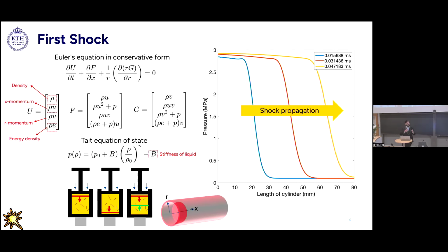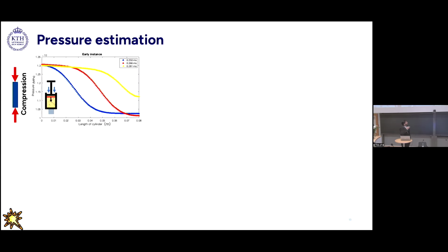And while the contact between the impactor and the piston is established, that will send in another shock wave, and that will interact with the reflected shock wave. This phenomenon will occur multiple times as long as the contact between the impactor and the piston is established. So if we want to see it in a bigger perspective, here you can see that after a few waves have passed, the shock wave no longer looks like a sharp vertical wave. It more or less translates as a horizontal component. And if you look at the yellow wave, which is a little bit later in the time step, it's actually going up at the bottom. So that means it has already started to reflect back.